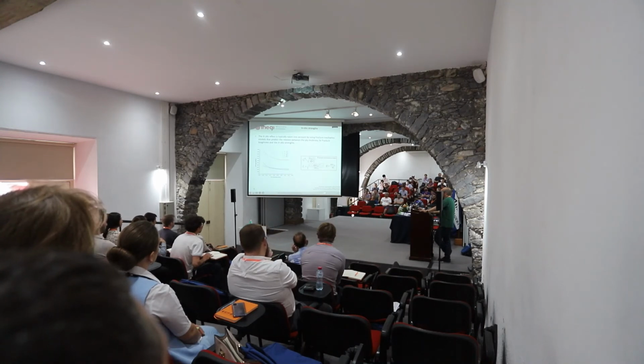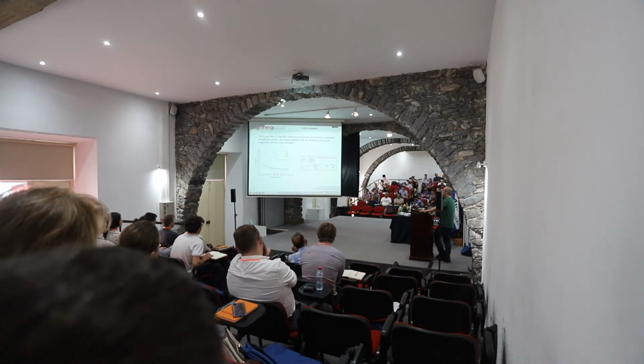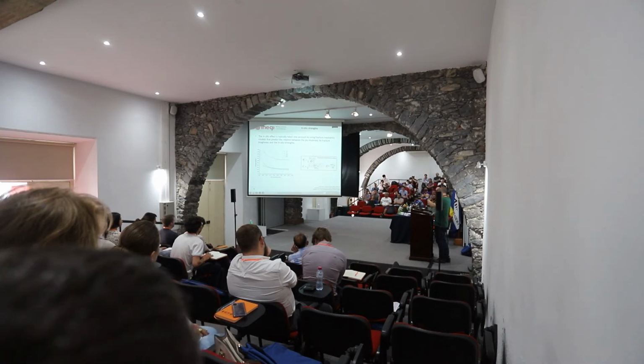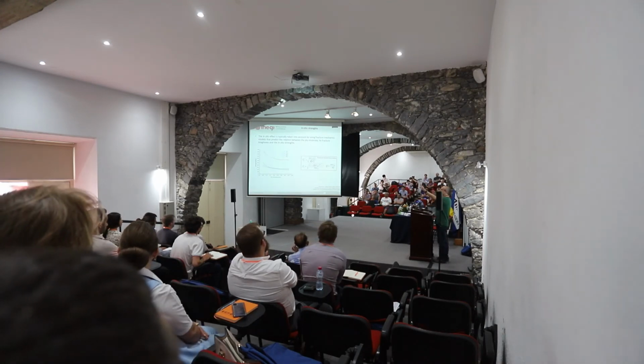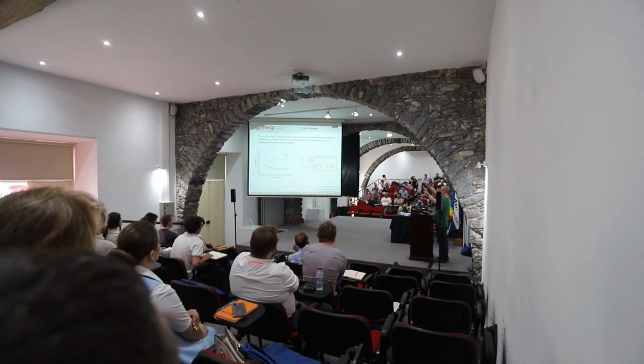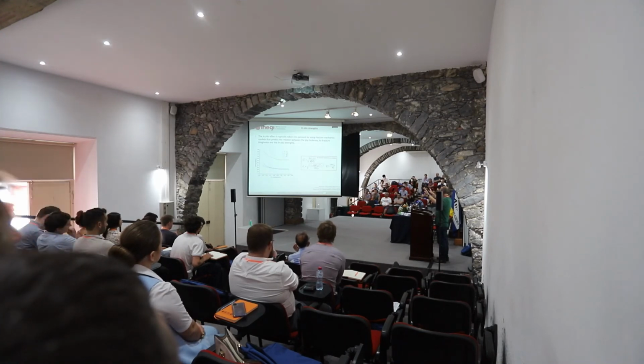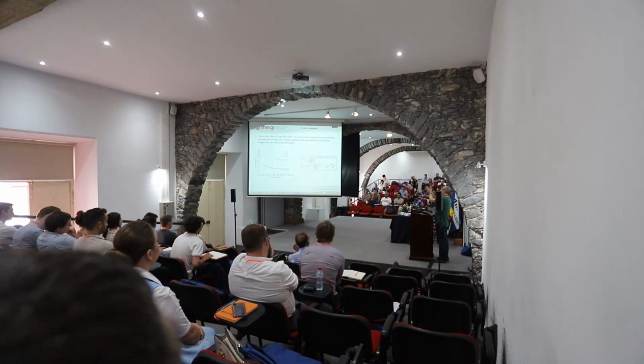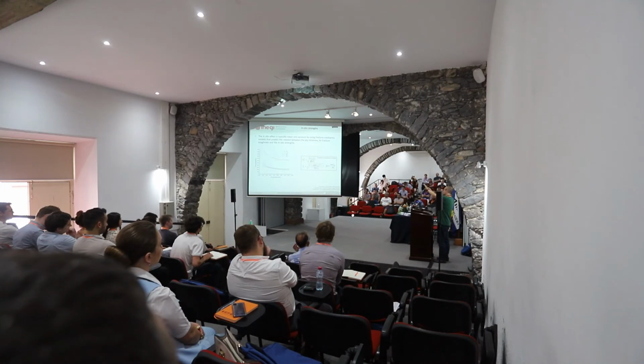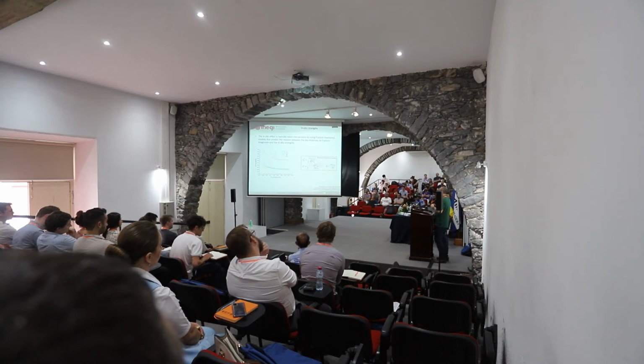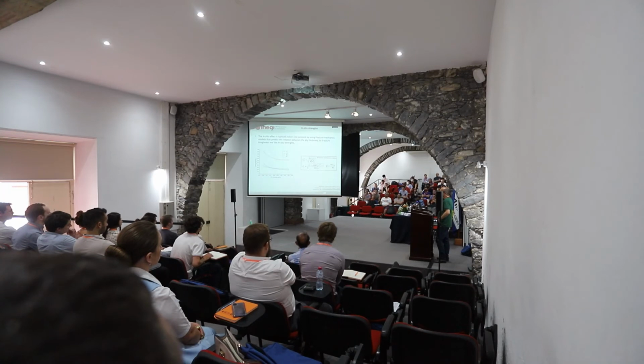So basically, imagine that you have some sort of analysis model, you have a failure criterion and you have to input some properties like the strengths, right? What we do is we don't use the strengths that we measure, the in-plane transverse tensile or compressive strength or shear strength from UD coupons, because we know the values are far lower than what we actually see in these materials.